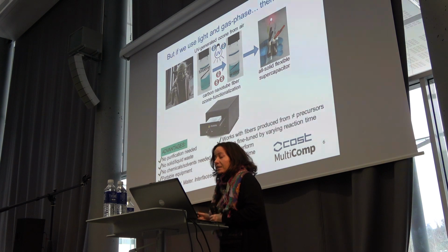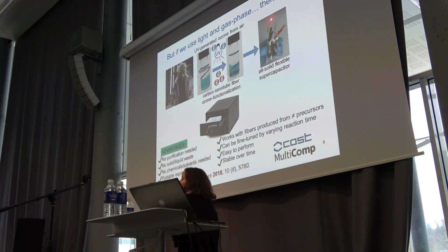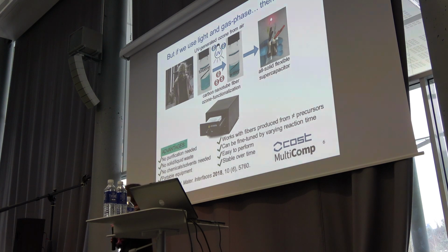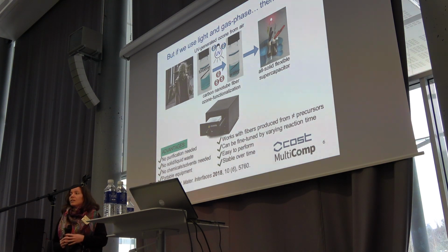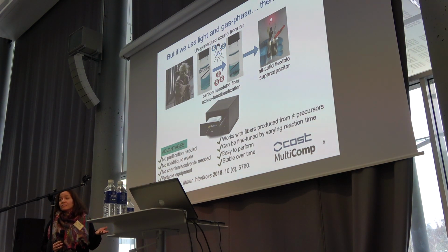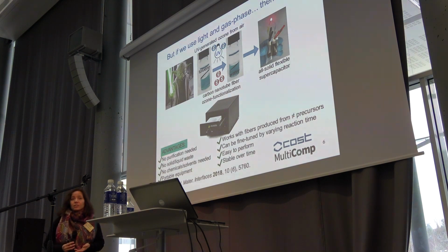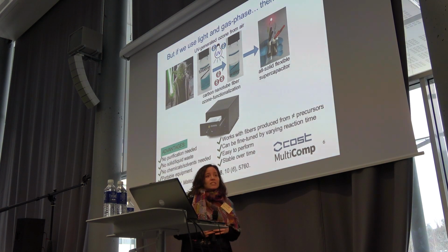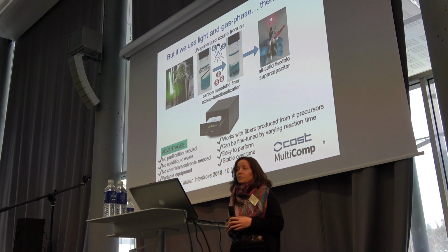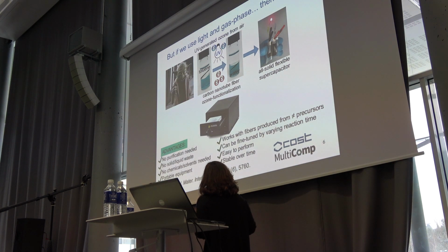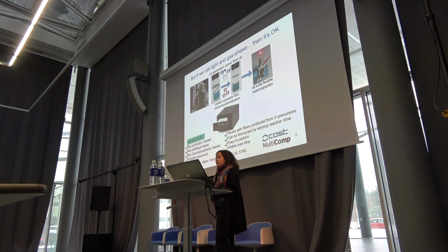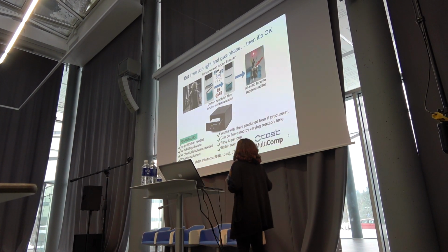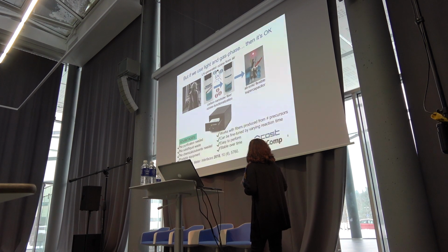So there are many advantages for this kind of functionalization, and of course we can apply it also to different kinds of carbon nanomaterials if you're interested. If you compare it, for instance, to the typical oxidation procedures that are liquid-based, you don't have to worry about purification, you don't have to use chemicals or solvents, no purification steps, no waste produced or to deal with, no solid or liquid waste. So it's very convenient. And also the equipment is small, so it can easily be carried around if you need to do the functionalization next to another piece of equipment for some other analysis.